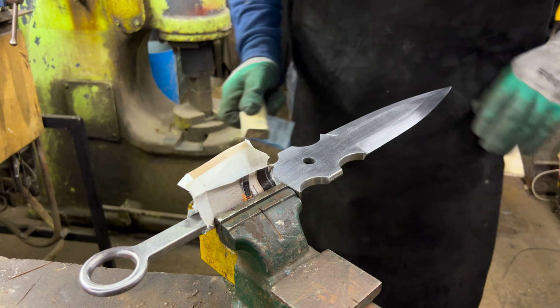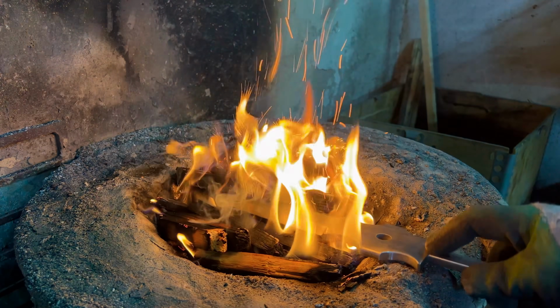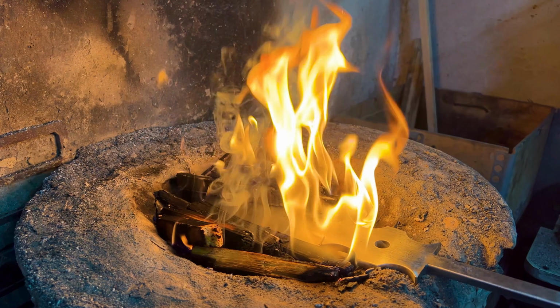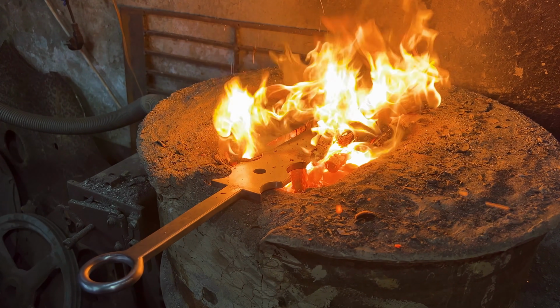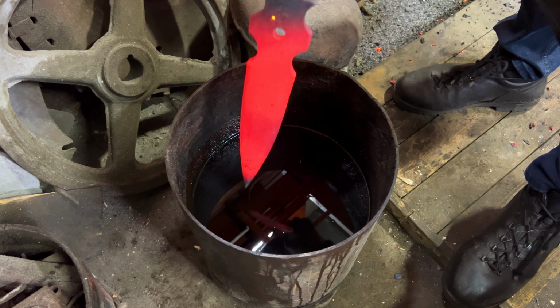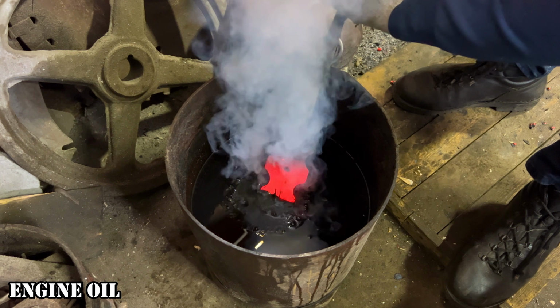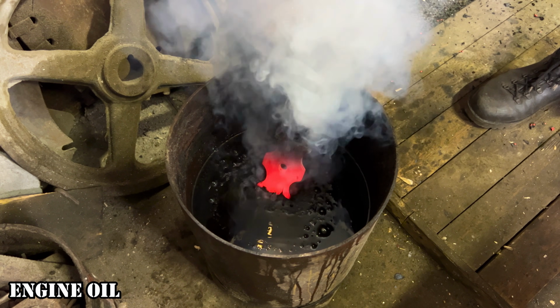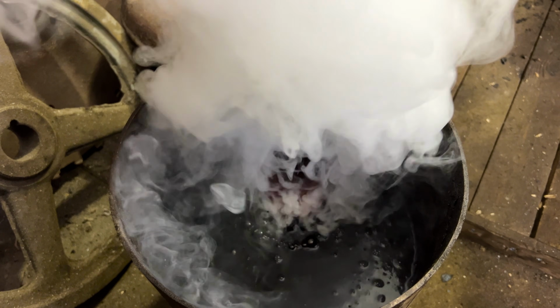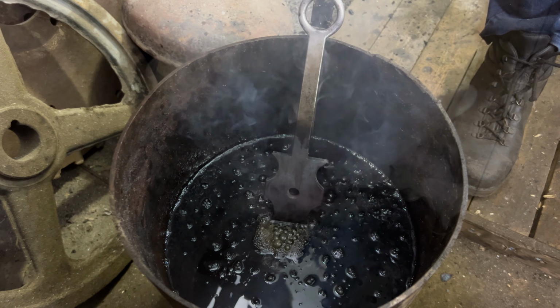Austenitizing at 820 degrees, non-magnetic range. I'm checking with a magnet. If it still sticks, not hot enough. If it drops off, perfect. That's our cue. Fast quench in warm oil, about 50 degrees Celsius. Cold oil risks cracks, hot oil's too slow and gives you a soft spine. Timing and temperature. That's the dance.